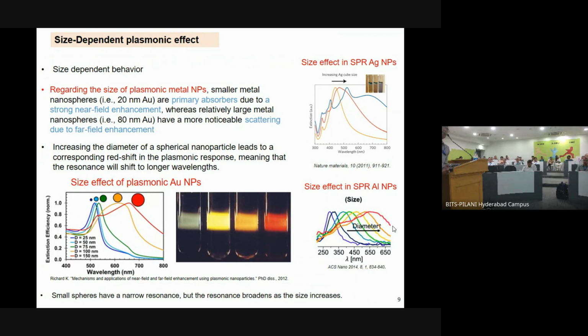In a way, you can tap more energy which is otherwise not utilized, because many a time we take a semiconductor, say TiO2, and then you try to modify the TiO2 band gap, but essentially if you bring it all the way from 3.2 only to around 2.9, that means the rest of the energy which you have goes unutilized. So the whole idea is, based on the earlier effects, how would you increase the light absorption cross section, or in other words light absorption. So that's where you see more amount of light can be practically used for these scenarios.